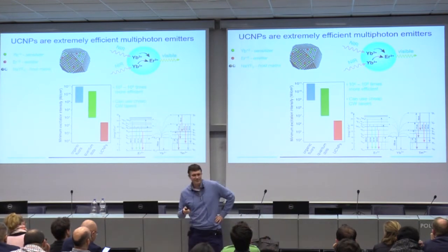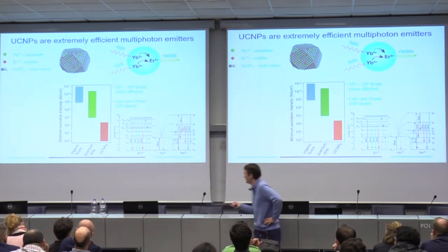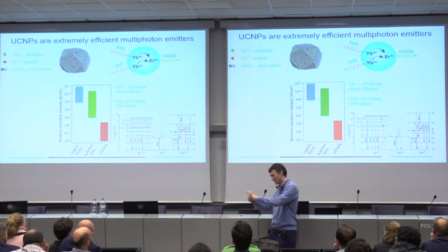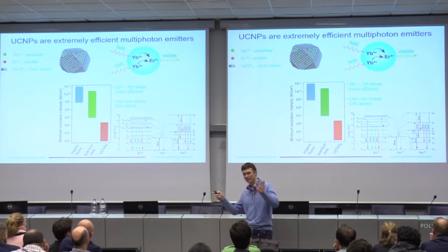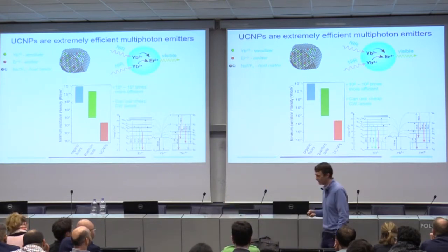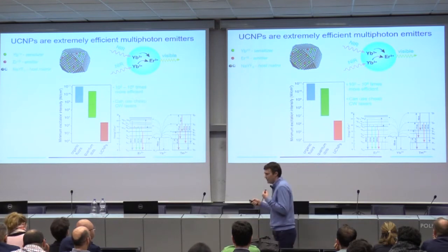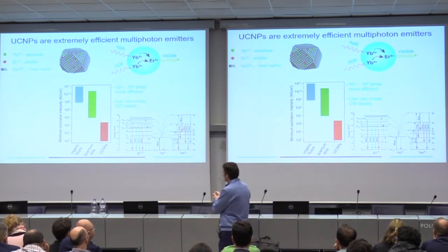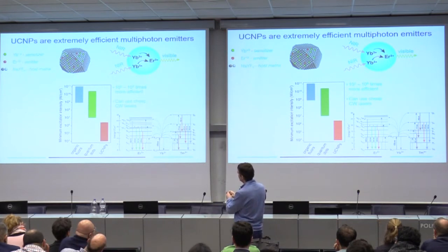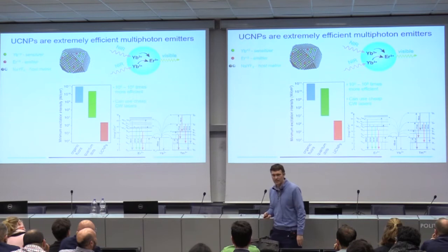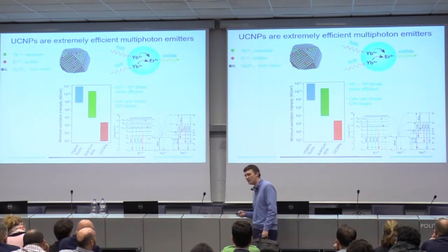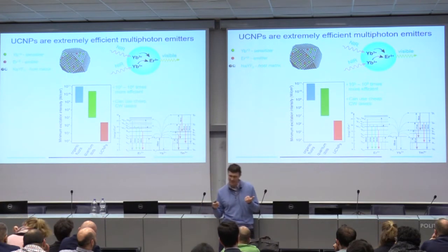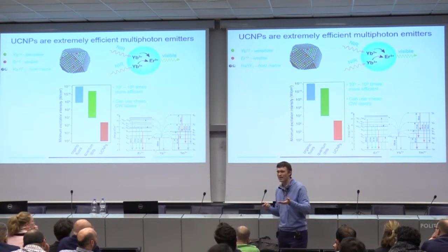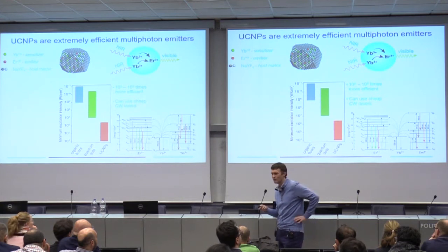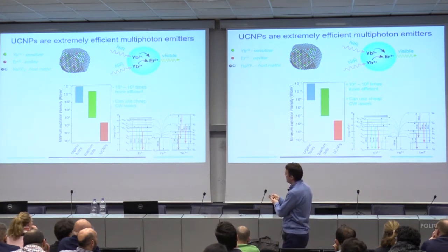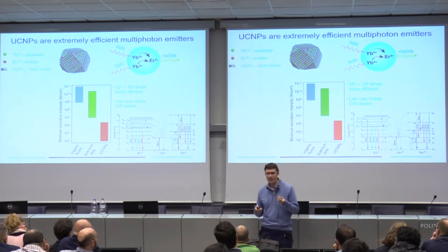And so why do these work so well? Usually, I put this energy level diagram in a small part of the slide because I breeze over it, but for this audience, I think it makes sense to explain it a little. Lanthanide ions are unique in that they have these very nice ladder-like sets of excited states. The good and the bad of these excited states is that they are optically forbidden transitions, so they don't really like to absorb light very much. But once they do absorb light, these excited states have lifetimes on the order of milliseconds.